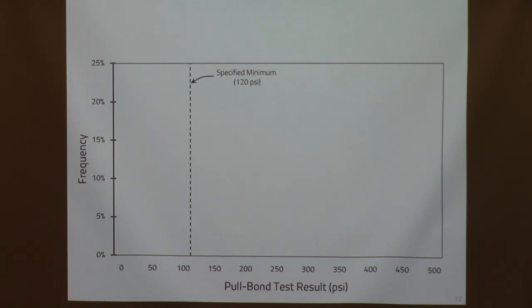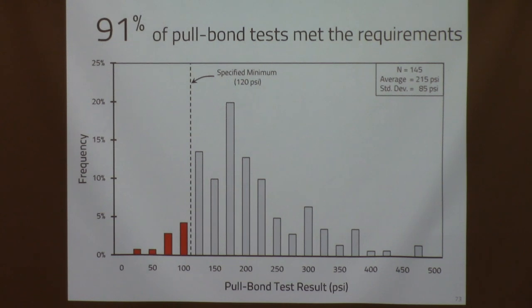We find out that if we can get 120 PSI test on average, we're doing good. We did 145 different pull bond tests over time. We had an average of 215. You can see the standard deviation of 85 PSI shows it's quite large. But we had some of these, you can see here. What do you do with those?